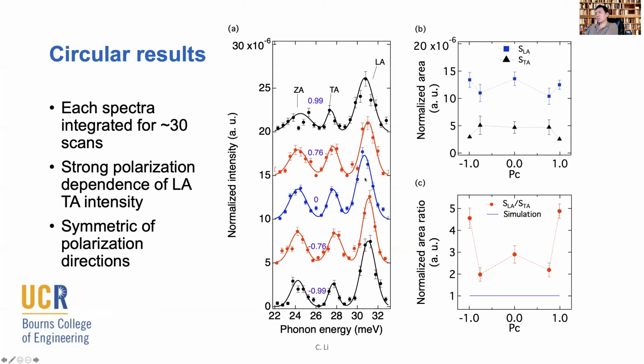there's definitely a change of the intensity ratio between the LA and the TA mode. In particular, if you look at the spectrum with the largest circular component, there's definitely a suppression of the TA intensity, as you can see here, and the LA intensity somehow got larger. If we plot the ratio between the LA and TA intensities, the ratio goes from somewhere near 3 to about 5 once we have the beam that is circularly polarized, well, we believe it has a big part of circular polarization. It's definitely not going to be 100% circularly polarized, but that's what we can do at the moment.